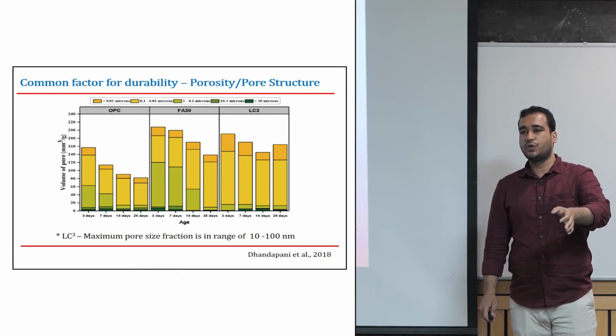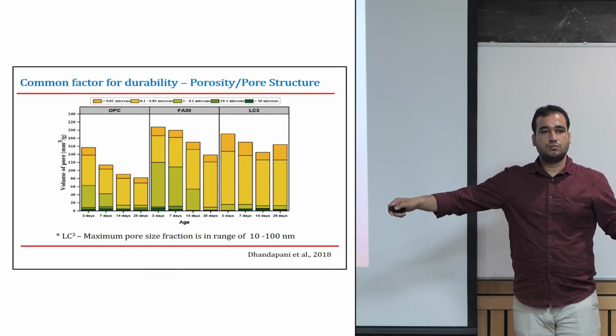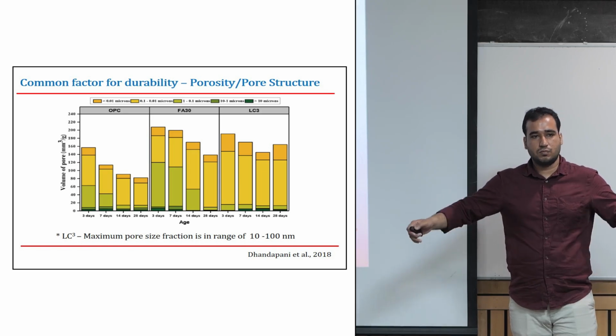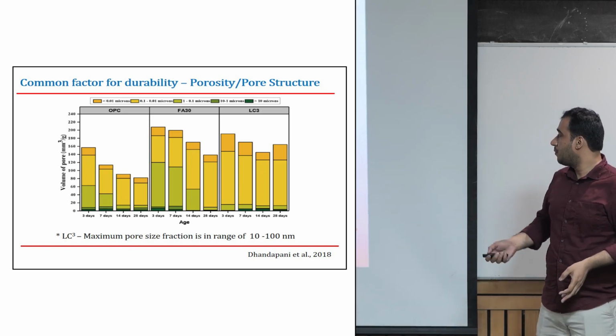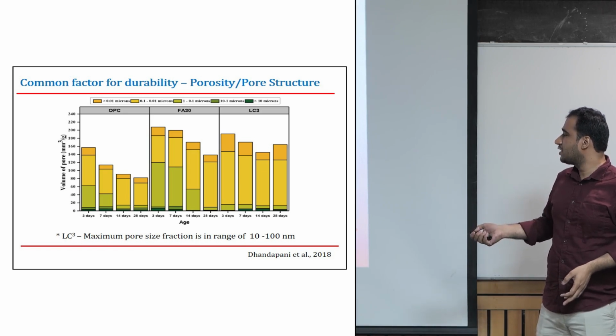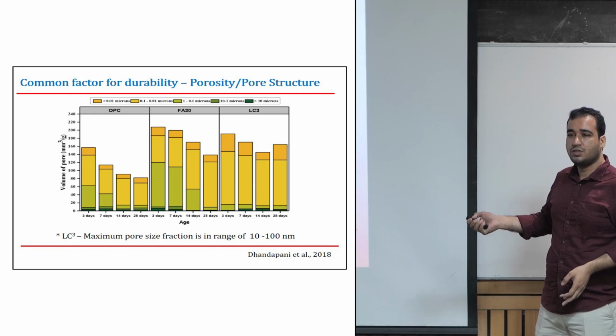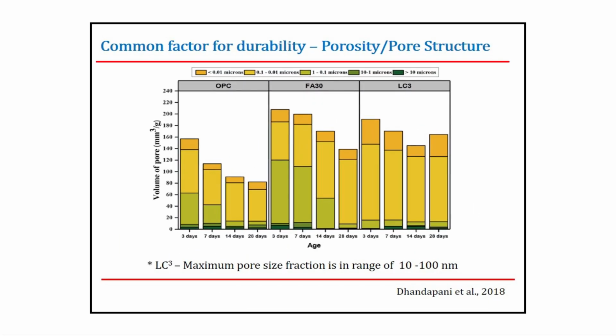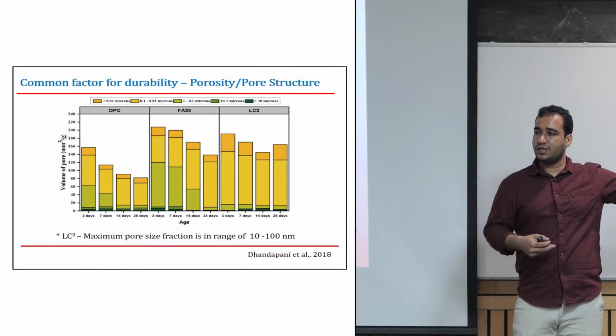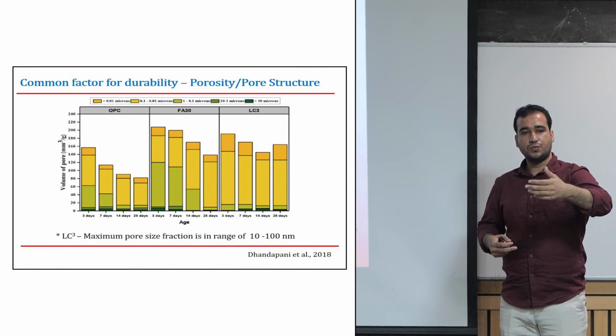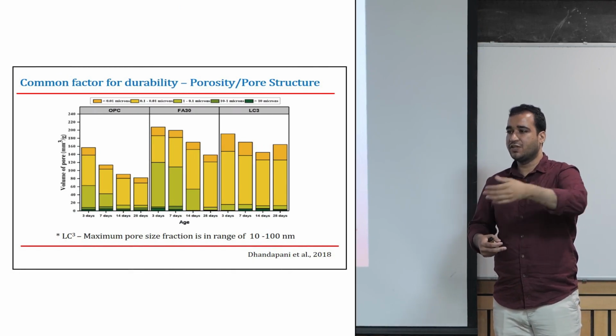In OPC, you have coarser pores from 100 nanometer to 1 micrometer, a huge dimension of pores. The major chunk lies in that. But when you come to an LC3 kind of system, you see most of the pores are 10 to 100 nanometers. And the chances of these small pores being not connected is much more than the larger pores being not connected. So we have to take care, when we talk about durability, that we don't just take one property and rely on it. We rather use 2 or 3 properties to properly characterize our material when we say if it's durable or not.